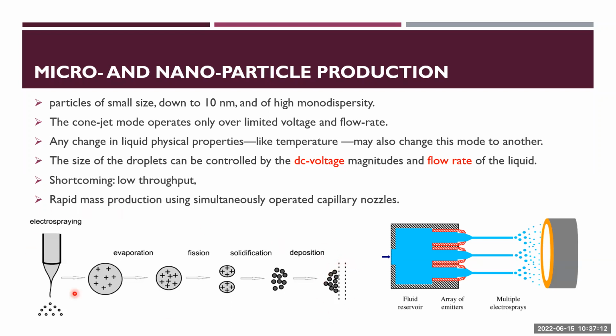This one needs a lot of optimization to get particles that are not sticky to each other, like well-dispersed particles. If you don't get dispersed particles, basically you will get a thin film here. So you just need to play with the parameters to convert between nanofiber, thin film, and particles.